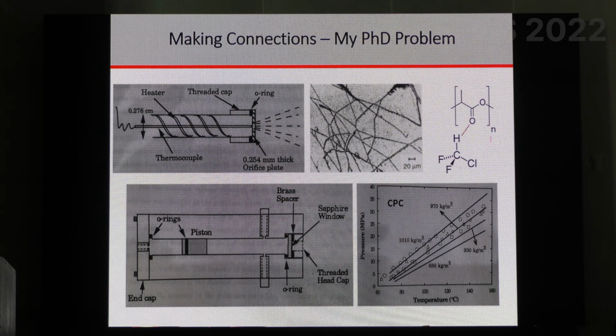I was working on an interesting problem of taking a biodegradable polymer. Even in those days, we were taking polylactic acid, polycaprolactone, these are all very biodegradable polymers. And I was trying to dissolve them in this molecule. Okay, it's R22, it's actually a refrigerant. It has 2 fluorine and 1 hydrogen atom. And this hydrogen atom is interesting because it can hydrogen bond with the ester group on the polymer, right?